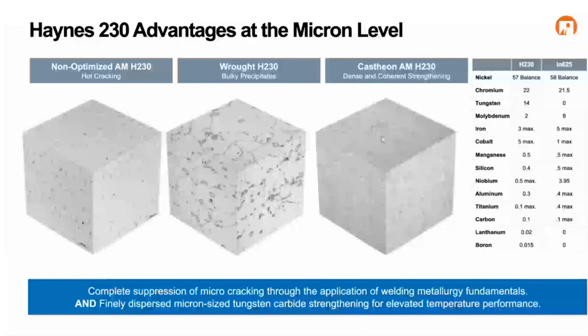So really what we're looking for here is this dense, optimized microstructure with the tungsten carbides forming after just a short heat treatment, again coherently within the grains.